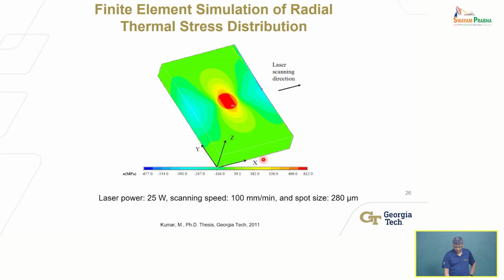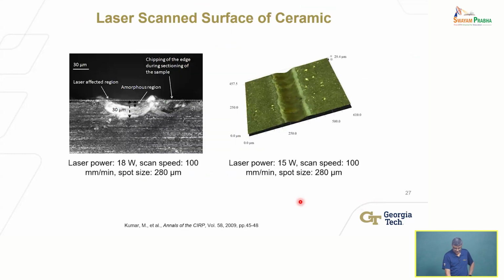So this is showing you the radial thermal stress distribution, in this case scanning in this direction at some point, for the same conditions, right? So I can do this using a finite element model or the analytical model. This is showing you what happens if I actually do this in an experiment. Same conditions, and I have scanned the surface of this reaction-bonded silicon nitride, and this is looking at the cross section. You can see here that there is a depth of affected region, 30 microns, according to what I can see from this image. And there is a small region here, outside of the white region, that actually is amorphized, okay?